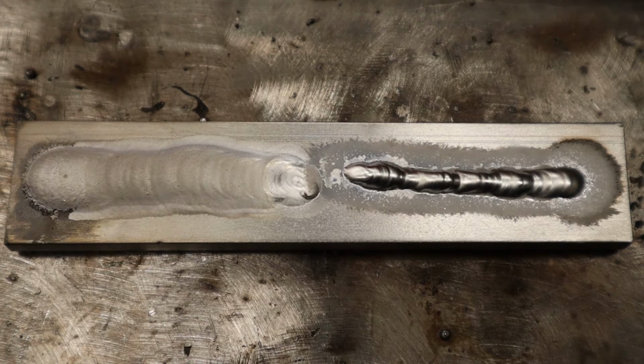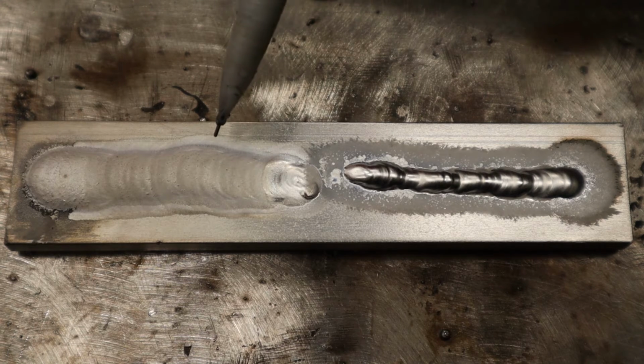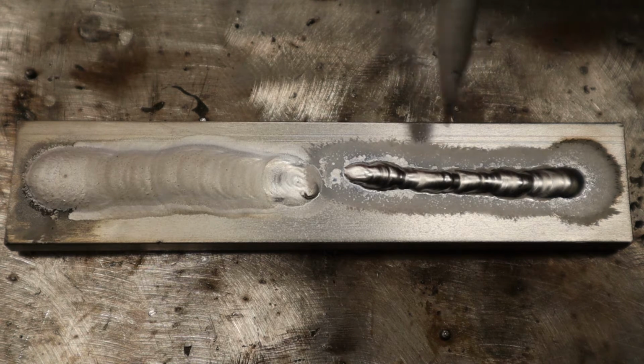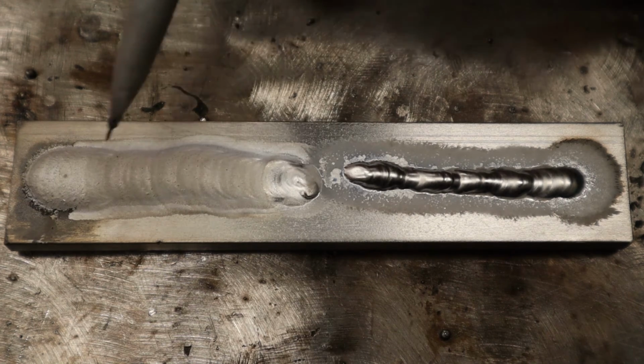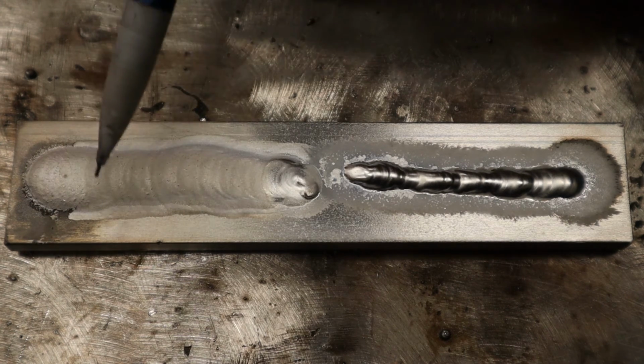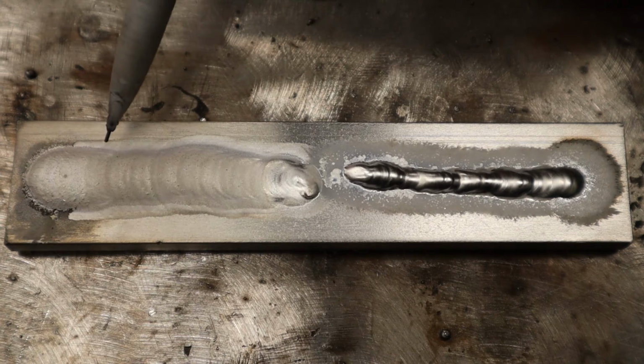All right, with these weld samples, I didn't change any settings except amperage so that I could show you two welds that are polar opposites. This is too hot and this is too cold. Now, if we look at the too hot, we've got a bunch of stuff going on here. The weld bead itself is too hot, so it's going to be flatter and it's going to go wider. In fact, it's almost to the edge of our cleaning action here.